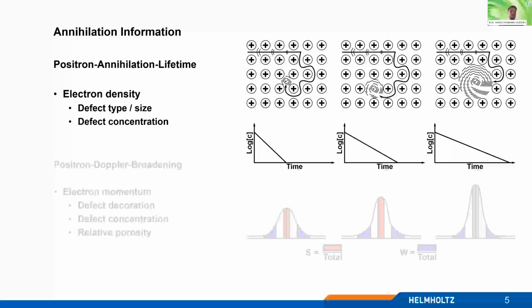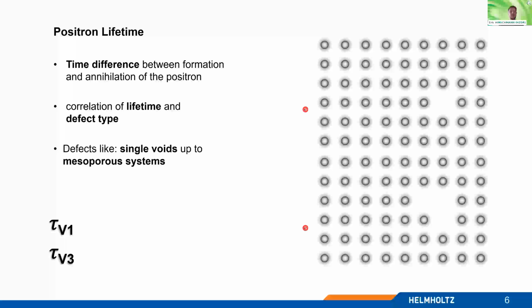But let's first focus on the annihilation lifetime or positron annihilation lifetime. How do we measure? So first of all, the implantation and the diffusion, and then it depends on the defect size. So the larger the defect, the longer the positron lives in the material. And this releases some kind of an individual property for single voids up to mesoporous materials, so in the range of 20 to 100 nanometers. So this 100 nanometers is more or less the maximum that can be investigated with positrons.